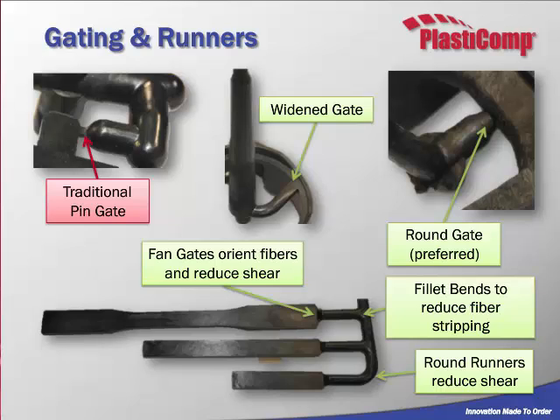We also recommend, as you see on the right, rounder gates and rounder runners. We find that really reduces your pressure also. Towards the bottom, this is an injection molded test bar set for flex, impact, and tensile testing. You can see here we use lofting and sweeping runner systems. You want to avoid sharp corners in these runner systems, so you also avoid breaking down your fibers more. Fan gates are very useful for aligning your fibers in the tensile direction also. Let's move on.